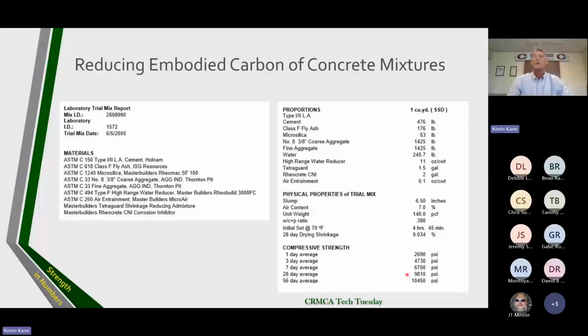Look at the compressive strengths I got out of air entrained concrete with a concrete mix that only had 476 pounds of cement in there. At 56 days, I had over 10,000 PSI. I don't know what we would do with this mix, but that was 25 years ago. Like I said, this mix has never seen the light of day.